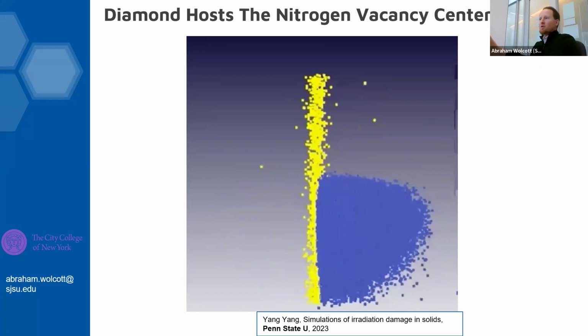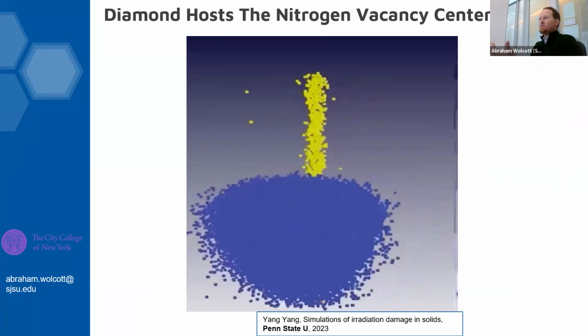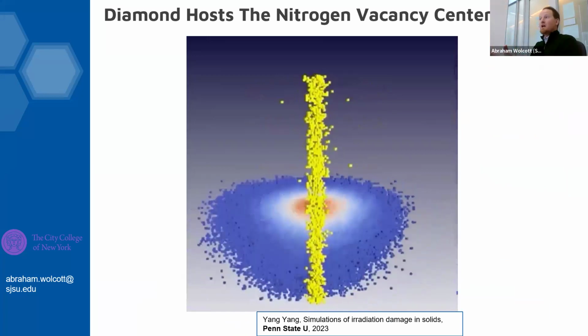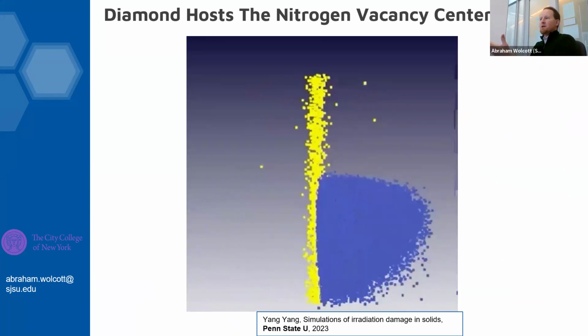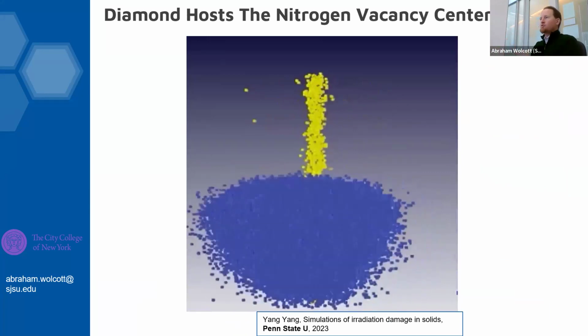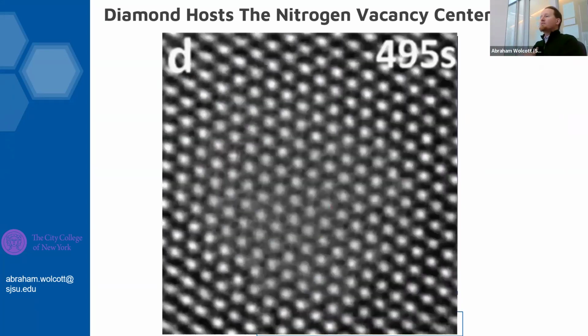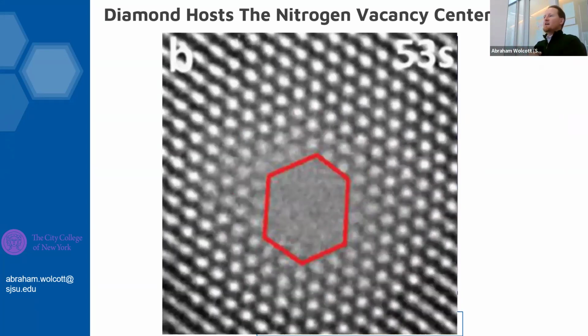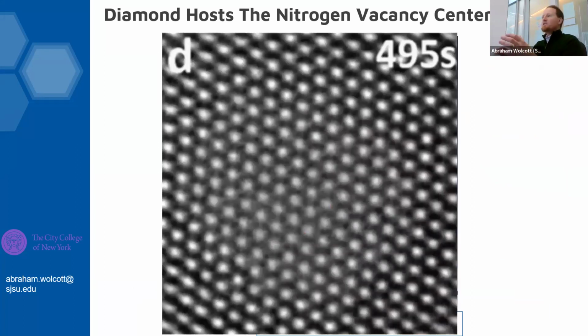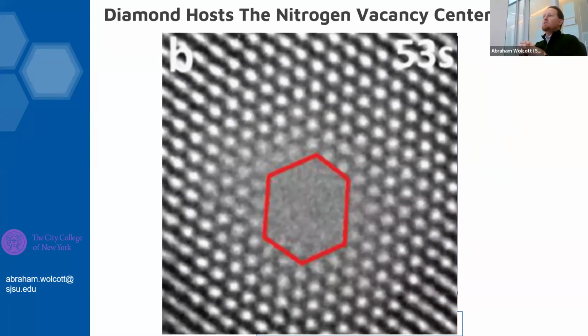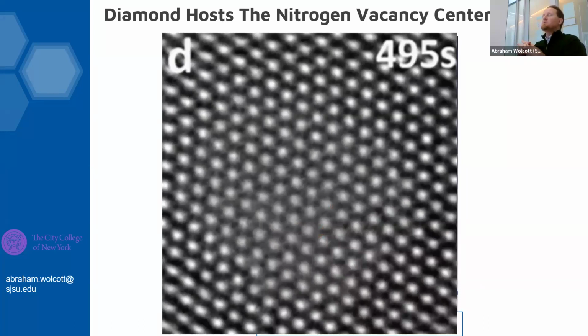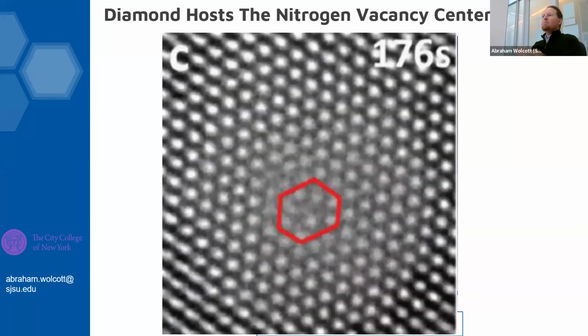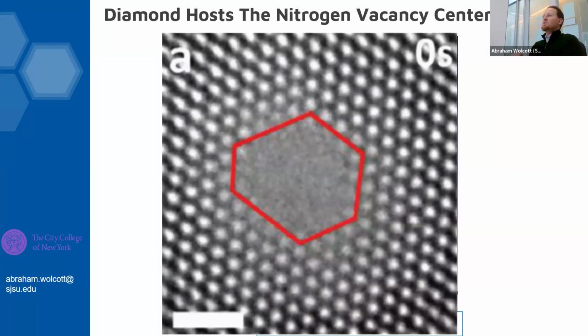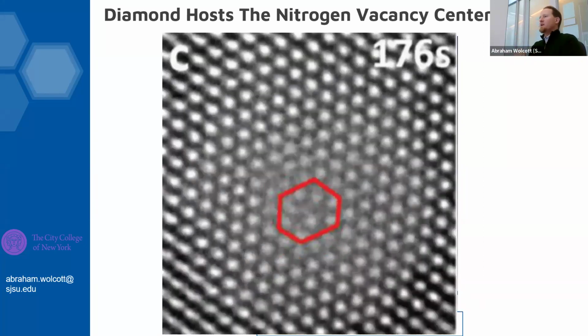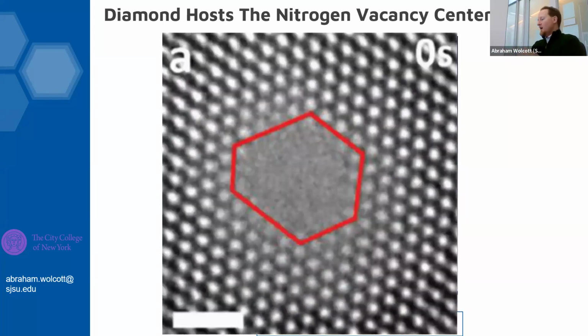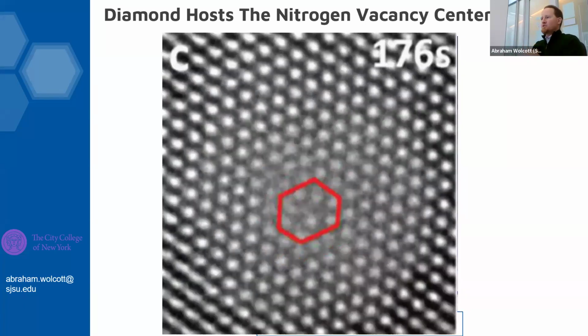If the nitrogen is already there, we would irradiate with any number of different particles. If it was a super clean diamond, like a CVD diamond, then we implant with nitrogen 14 or nitrogen 15. We then have vacancies that are generated inside of the material. These vacancies will then percolate and move during our high temperature annealing steps, and we'll be able to have most of the vacancies actually get annealed out, but every once in a while the vacancy will land next to a nitrogen, and we'll have our NV centers now activated.